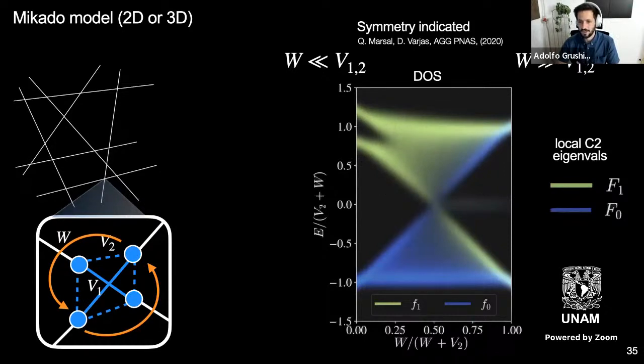And you'll see that essentially, when W is equal to 0, then this molecule actually has C4 symmetry, which is colored here. So these are the even and odd eigenvalues of C2, and so you see that they're exactly an eigenstate. And what Weaire-Thorpe predicted was that the color remains well defined in the edges of these bands, which is what we see here. And so we can see that the eigenvalues kind of invert, and now the filled eigenvalues change. And what this means is that the symmetry eigenvalues that I was showing at the beginning for crystals are changing, but now for an amorphous system. And what we see also is that there's this little weight here, which is nothing but the edge states that I was showing before.